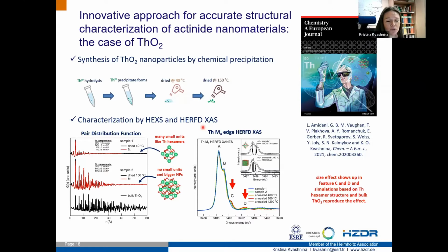First we thought we would record the data and surely understand the difference between nanomaterials and the bulk system. But nanoparticles are quite hard to study, because all spectral features become broad just because of the nano effect. And then you always have a doubt: is it really the nano size, or is it a crystal modification which took place? I'm talking about the data reported in the middle. You see that features after the post-edge features B and C start to disappear in the case of the nanoparticles.